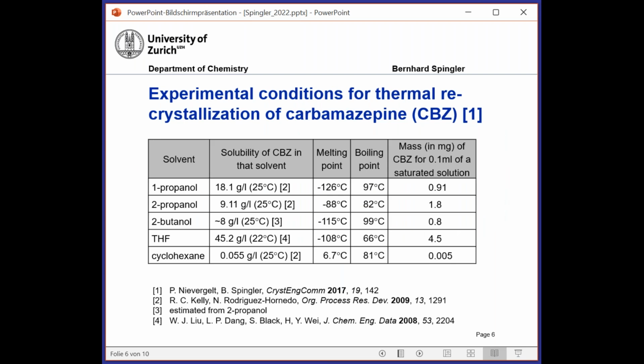The first compound that we tested is carbamazepine, a well-known compound in the crystallization community. And here you already see some differences to the isothermal crystallization, where you use vapor diffusion, a solvent and an anti-solvent. In this experiment, we only used one solvent. Of course, you could also work with solvent mixtures, but for simplicity and to start with, we just work with one type of solvent at a time. And this type of solvent determines how much the solubility is. Obviously, this is solvent dependent if we work with the same compound. You might think that if we want to minimize the compound consumption, then cyclohexane, the lowest example in this table, would be ideal.